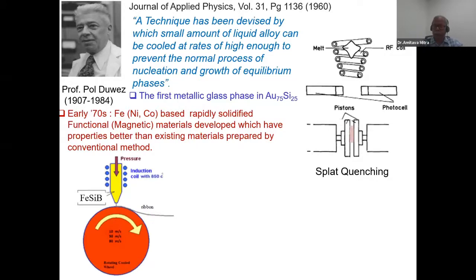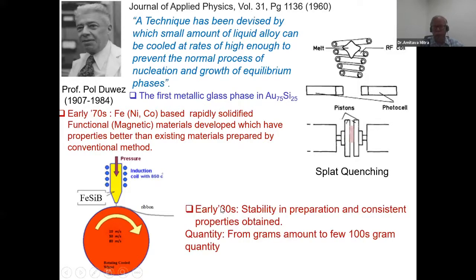Then different innovations took place from this invention: how we can go for, instead of a piston, a copper wheel which can rotate. And instead of this drop which is coming, there may be a crucible, that is the quartz crucible, which is heated by induction heating, and the liquid alloy is there, which is heated. This may be iron, silicon, boron, and we can get it in the form of ribbon.